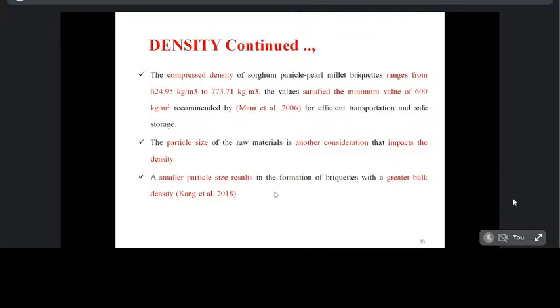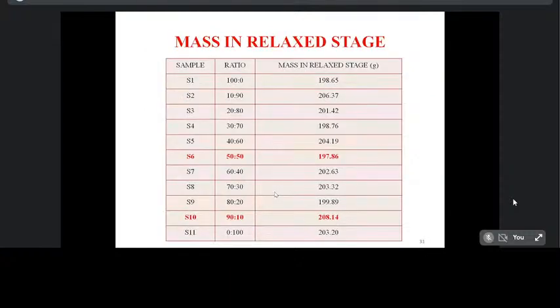The particle size of the raw materials is another consideration impacting density, because a smaller size of the agricultural waste particles gives higher density. Okay, so mass in relaxed stage. This table shows the various samples having various mass in relaxed stage. The samples S1 to S11 have very different mass in relaxed stage. So sample S6 has the lowest mass in relaxed stage, that is 197.86 gram for the sample ratio 50:50, and sample S10 has 208.14 gram for the sample ratio 90:10.